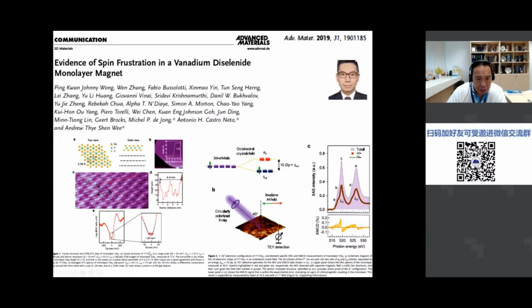And these here are the STM images. They show interesting charge density wave patterns which have been reported separately, and we are also working on another paper on some of this. And you see in this phase, it's semi-metallic, and there is a small band gap here. This is the 1T phase, I believe. And yeah, so although theory predicts that it should be magnetic, we did not observe magnetism.